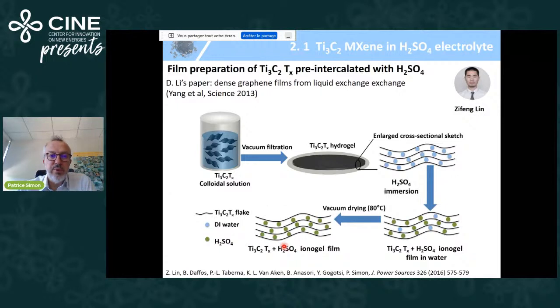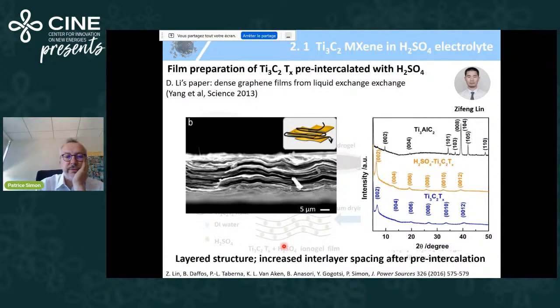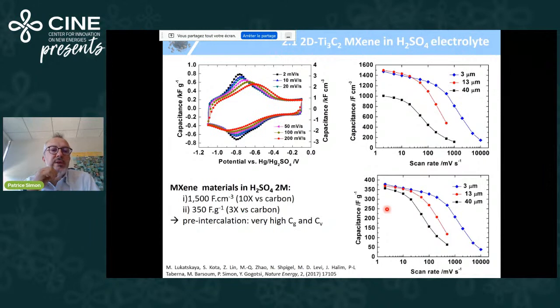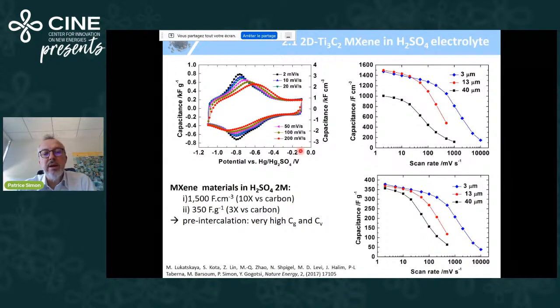We planned to obtain pre-intercalated Ti3C2 materials with H2SO4 electrolyte. And when you see your electrode, this is a filtered electrode, so it is very thin and flexible. You start from the MAX phase here, Ti3AlC2. This is the MXene, so you can see that the 002 peak is shifted to a lower angle, so that you increase the d-spacing. And then when you put sulfuric acid back into it, you shift a little bit more because you increase the interlayer spacing after the pre-intercalation of sulfuric acid. So everything is fine. And now when you test this material in sulfuric acid, you can see in this cyclic voltammetry a very symmetric cyclic voltammetry with surface redox, symmetric peaks, and you can reach super high potential scan rates.